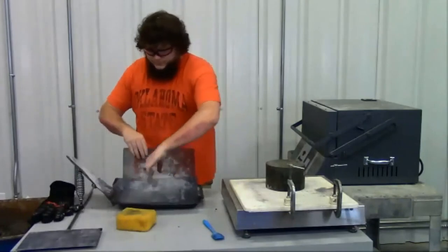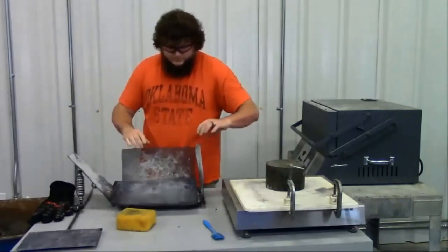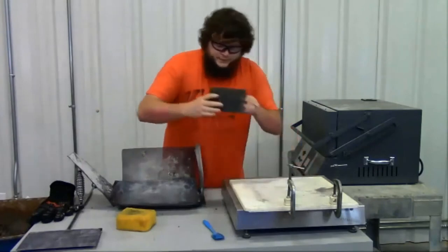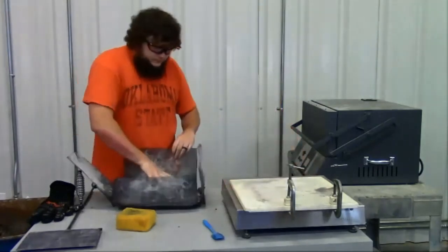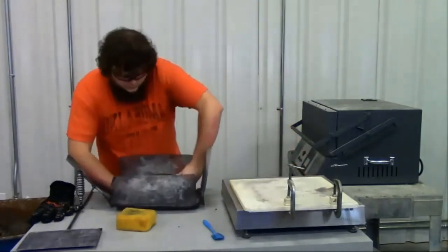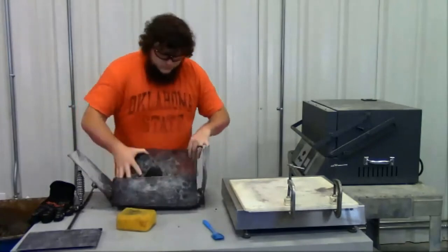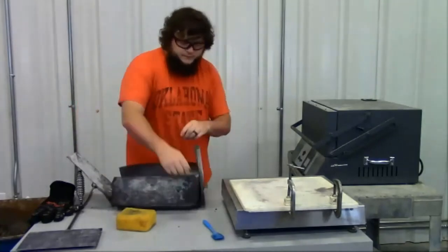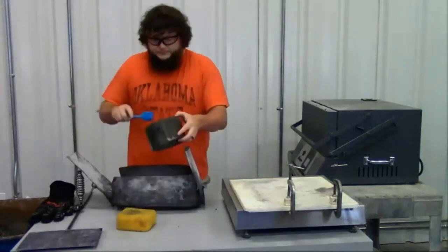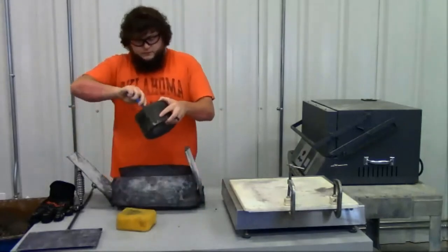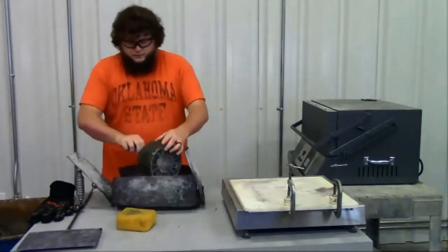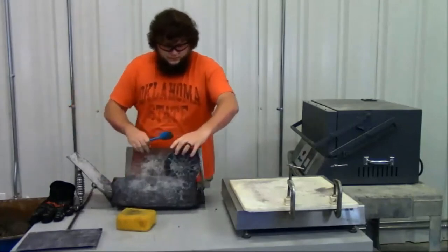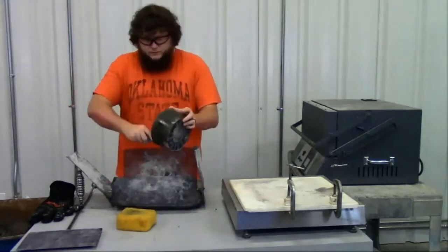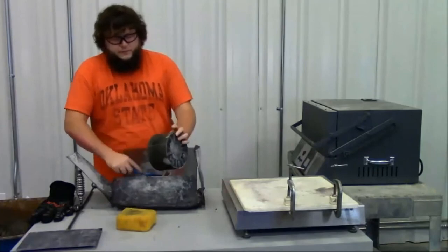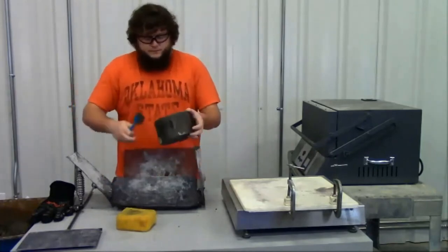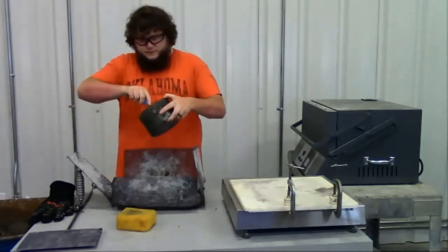After you've recorded the weight, dump the concrete cylinder into the wire mesh bag on top of the pan. Use a silicone spatula to remove as much concrete material as you can from the cylinder mold. Make sure to scrape it well. It needs to be within 10 grams of the initial empty cylinder weight.